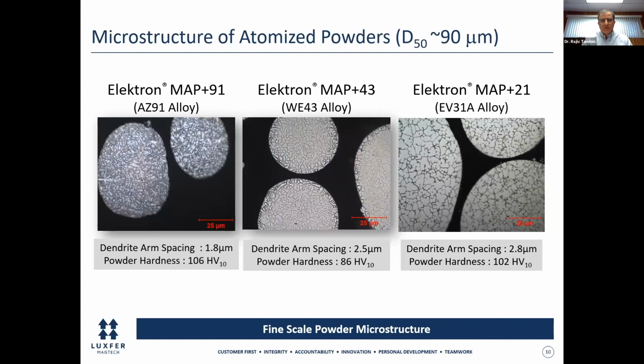Now, one of the key things to keep in mind is when you start with an atomized powder, in this case with these alloys, I've shown you examples of AZ91, WE43, and EV31, one of the advantages you have is you're starting with essentially a really miniature casting with very, very fine scale microstructure. And the groups that have worked with these alloys in additive manufacturing go on to report properties which seem to be very promising, but it all starts from having the fine scale structure in the powder.